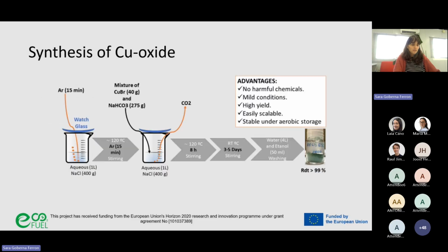In this project, we synthesized a copper oxide catalyst in aqueous media under argon using simple inorganic precursor salts. The formation of the copper oxide material was monitored by a clear color change of the suspension, and the final material was obtained with very high yields. This process relies on mild conditions. We didn't use any harmful chemicals, and it was easily scalable.